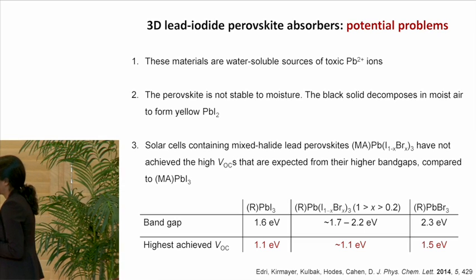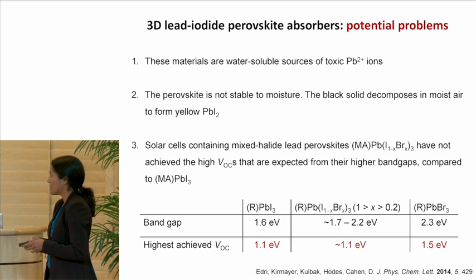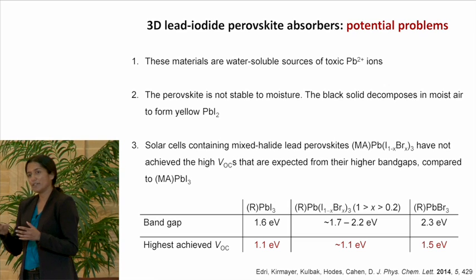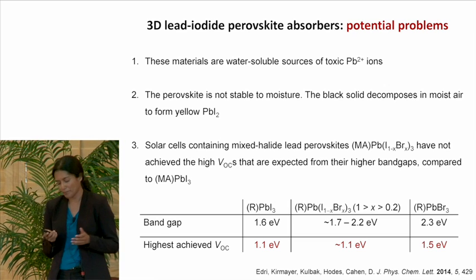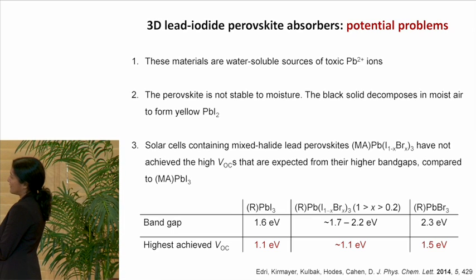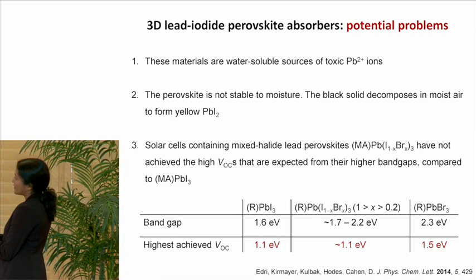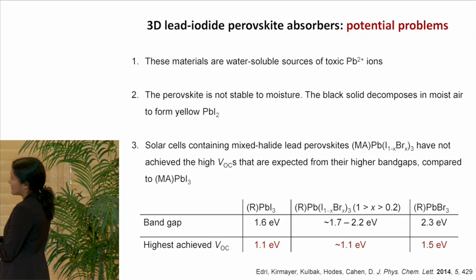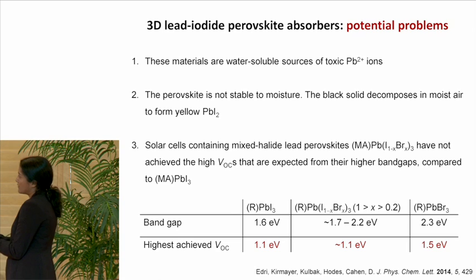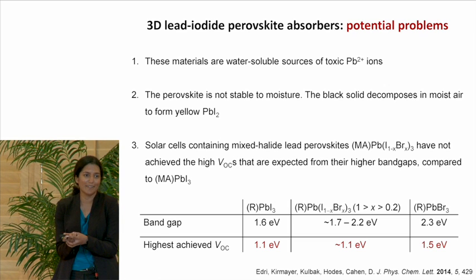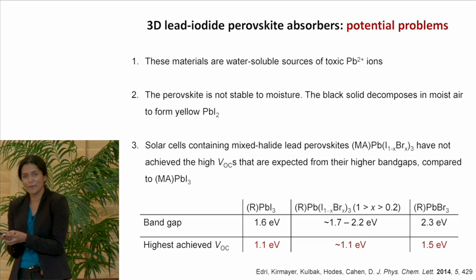And the final point I want to bring up is something that has become more apparent recently. I told you that by adding bromide into this lead iodide lattice, we can change the band gap. So we can form materials that have a band gap of 1.6 eV using a lead iodide lattice, as well as a material with a band gap of 2.3 eV using a lead bromide lattice. And by using intermediate stoichiometries of iodide and bromide, we can actually access all intermediate band gaps. But when we look at the voltages that have been achieved using these materials, the lowest band gap material gives a low voltage, the highest band gap material gives a high voltage, but the intermediate band gap materials do not give higher voltages than the lead iodide material, and this is very curious. So we decided to investigate why this might be as well.